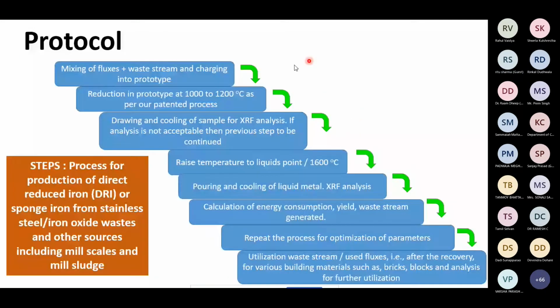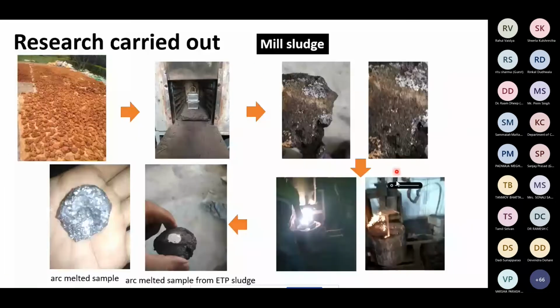You can see the step over here, certain fluxes. Flux is nothing but different chemicals. It is a proprietary chemical we utilized for the reduction of the oxides available in the sludge as well as the mill scale. In mill sludge, we can put it again into the electric arc furnace, and we identified that the arc melted sample is as good as that taken out from the blast furnace. So metal with around 95 to 97% iron is produced from this sludge also.